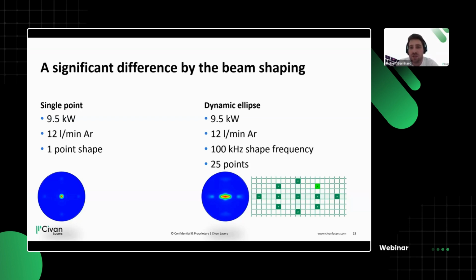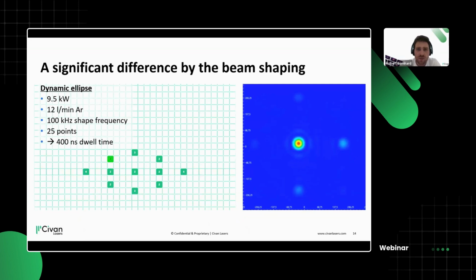So what we developed is a dynamic ellipse that has 100 kilohertz of shape refresh frequency and consists of 25 individual points. You can see how this is made up here in our program on the bottom, and it's important that our welding is aligned orthogonally to this line. So the leading edge is on top, and this makes for an especially wide weld seam. And of course, using the scanner rotates, like we saw with the 2 dots, it also rotates this ellipse electro-optically. So this means, like we were talking about, this is really, really fast.